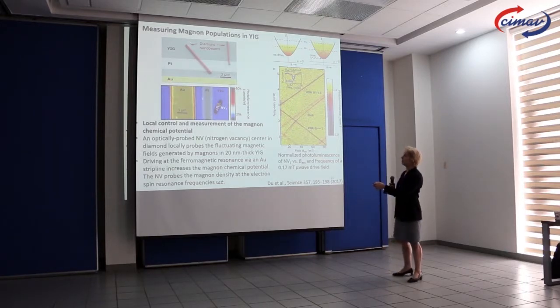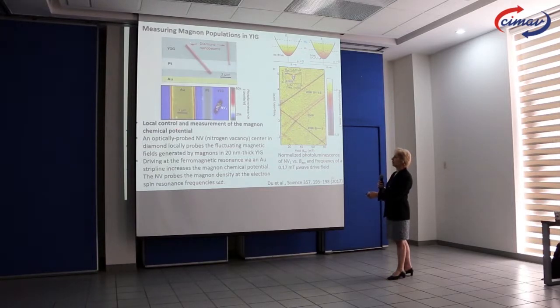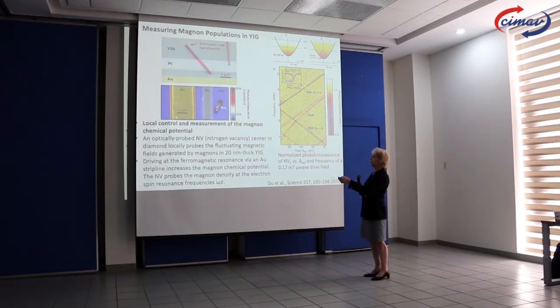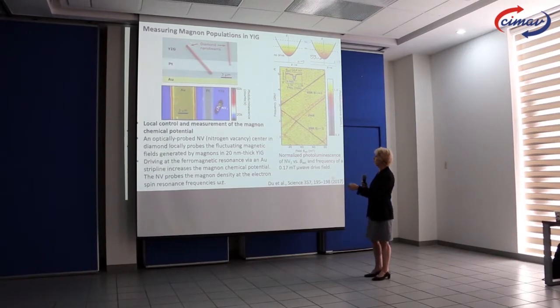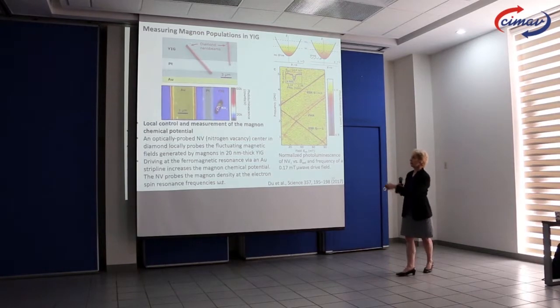And what we did here was we used it in an experiment where we could detect this population of magnons that was excited in the YIG using nitrogen vacancy centers in diamond. So this red thing is a laser beam. This was done at Harvard by Amir Yacoby's group.